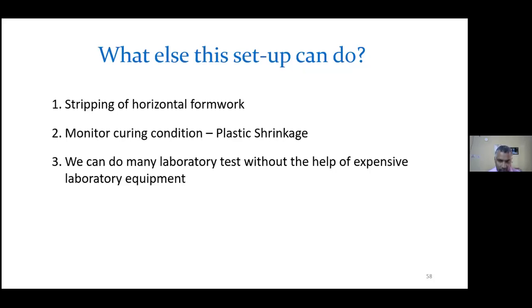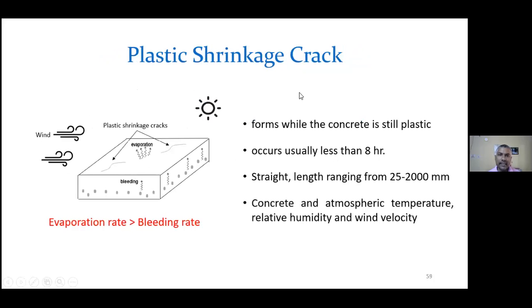And if you are interested, I want to show a couple of slides on this, the plastic shrinkage crack. When you cast a concrete, bleed water comes out to the surface of the concrete, and if you have a higher evaporation rate due to wind, humidity and the atmospheric temperature, then you find cracks and you require curing water at that point of time. But many times in real construction sites, people are not giving attention to curing. So we thought to check this evaporation rate and bleeding rate through this sensor and get the information to the project manager, so that he can intervene and take necessary measures for better quality.